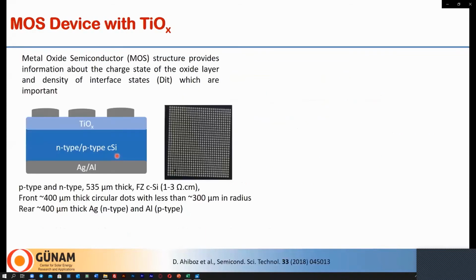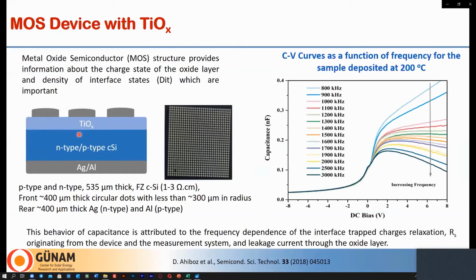Later on, we studied those titanium dioxide films by CV measurement. As you might know, a metal oxide semiconductor structure, as shown here, may provide information about charging states of the layer as well as interface state density. We fabricated this device on both N-type and P-type wafers, and we measured CV characteristics, as you can see here, as a function of frequency. This frequency dependence is typical in CV measurement if you have interface trap states, a series resistance effect, or some leakage current in the device, which is typical in such structures.